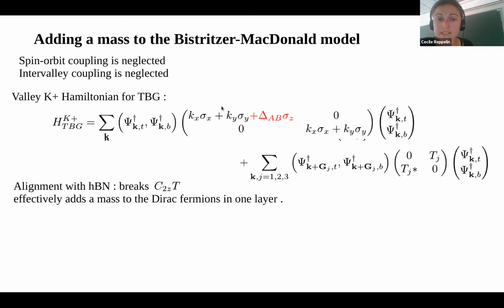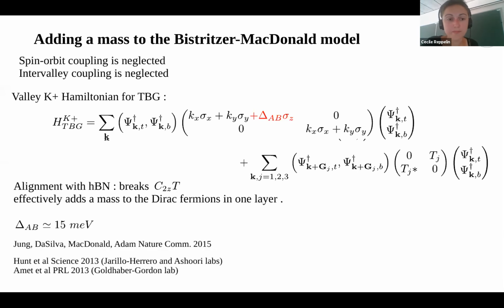And note that I've only added it to one layer and not to the other, because typically only one of the graphene layers is aligned with the substrate for practical reasons. But this is enough to open a gap in all of the Dirac cones. The amplitude of this mass is around 15 milli-electron volts, and this is a gap that was experimentally observed in these experiments, and later analyzed theoretically.